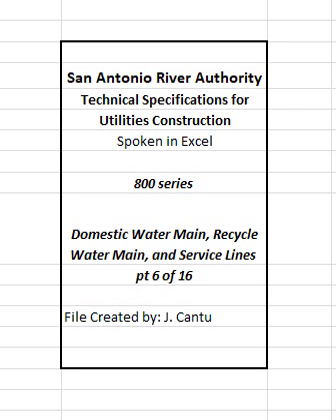B. Gravel subgrade filler composed of well-graded, crushed stone or gravel meeting the following requirements. Passing the 2 inch sieve 100%. Passing the 1-3/4 inch sieve at least 95%. Passing the 1/4 inch sieve at least 90%. The crushed stone or gravel shall have an abrasion of not more than 40 when subjected to the Los Angeles abrasion test.